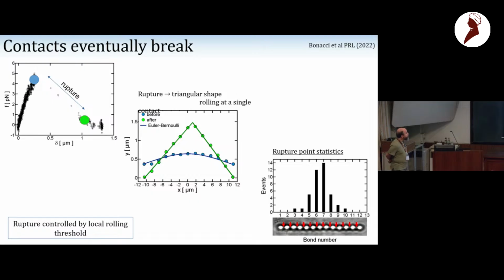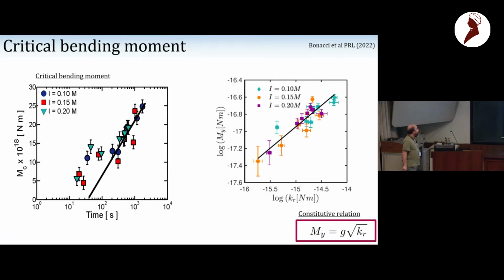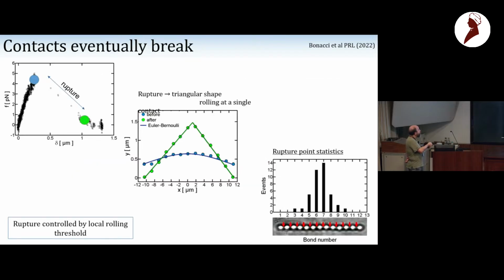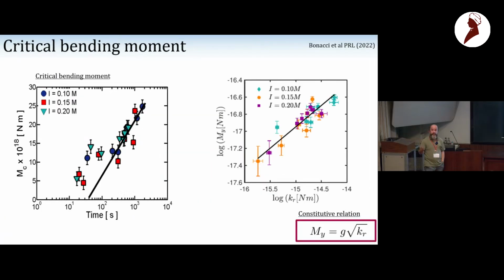So eventually contacts rupture. When you have rupture, rupture occurs usually at the center. I mean, that's rupture point statistics. It occurs at the center. And it tells you that rupture is controlled by a local rolling threshold. Okay, so basically we play the same game. We have rupture. We can construct the rolling threshold. The rolling threshold also depends on time. And we find a relation between the rolling limit and the bending stiffness of contacts.